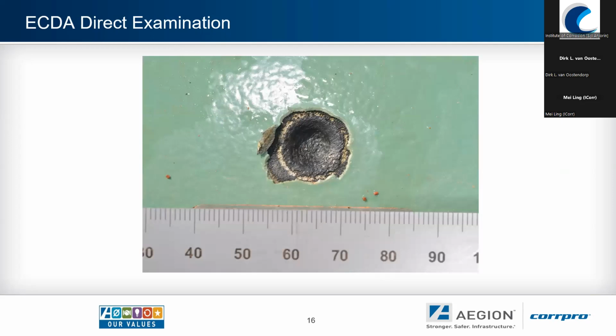Typically other kinds of things that have been found. This was one area where there was also AC corrosion that was identified. So with the current attenuation, we identified a number of these small points. DCVG pinpointed them, and the CIPS identified that there were low potentials as well when they were excavated. There was a metal loss anomaly that was a result from AC corrosion that had taken place due to the power line crossings.